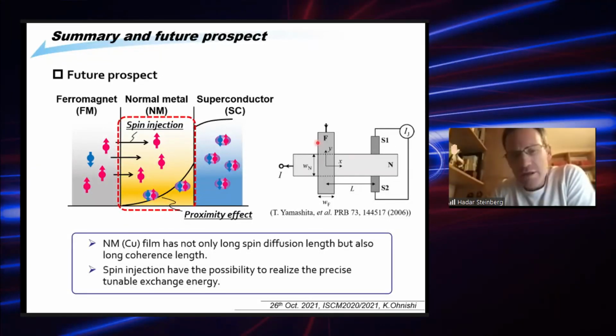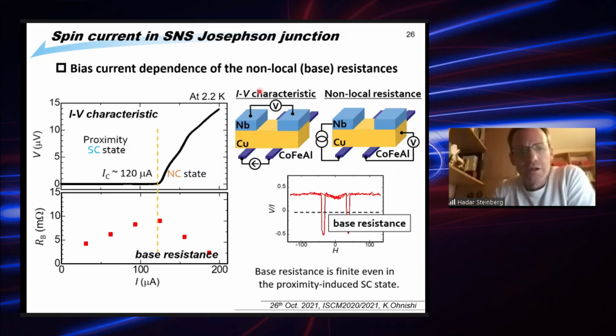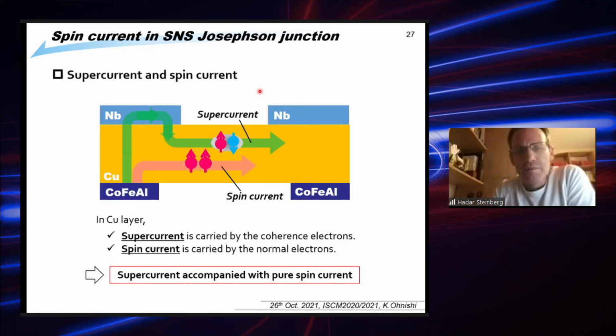I'm wondering, regarding the last couple of slides that you showed with the coexistence of normal carriers and proximitized carriers in the copper, whether there's a possibility of looking at the system using something like a Tinkham-Clarke experiment, where you try to see if the superconducting carriers and the normal carriers are in equilibrium. I have to disclaim that this experiment was done on a superconductor, not on a proximitized region. But is there a possibility that these two populations are out of equilibrium? So you have proximitized carriers which have one potential, whereas you have spin polarized carriers which have a different potential. And how much can you say about their coupling within your channel?